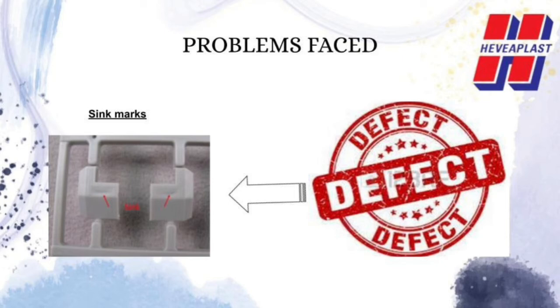They can also be caused by inadequate pressure in the cavity or by an excessive temperature at the gate. All else being equal, thick sections of the injection molded part take longer to cool than thin ones and so are more likely to be where sink marks are located.